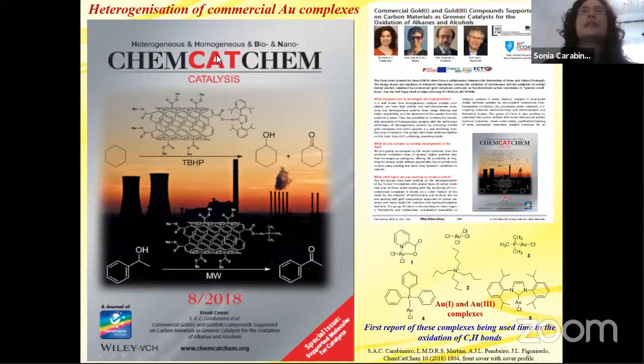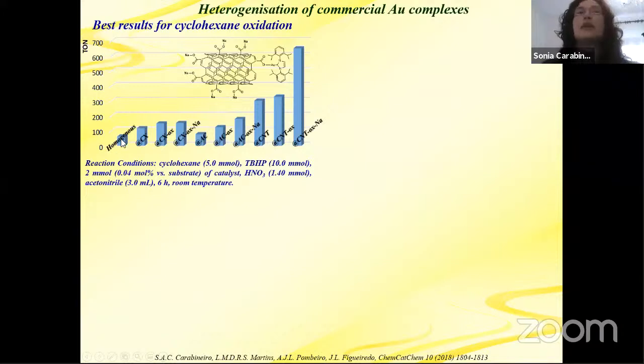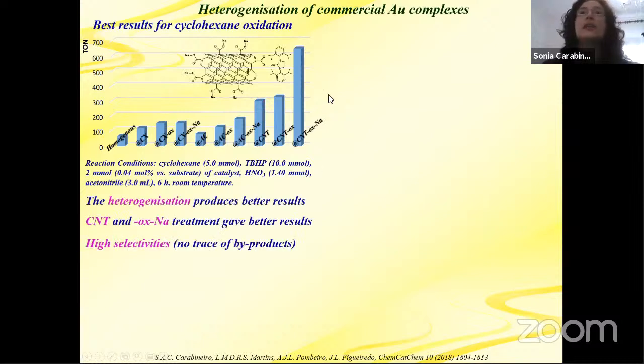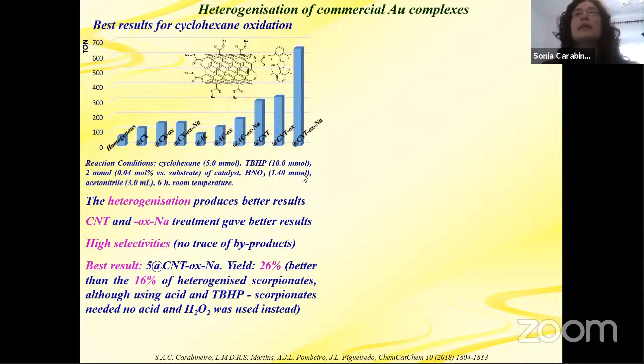So here, some example of results with the heterogenization of this complex on the carbon nanotubes. We see here again homogeneous, and if we heterogenize, we obtain better results. So heterogenization is better. Again, carbon nanotubes give the best results, especially with this oxidation treatment with sodium hydroxide, and again high selectivities with no trace of byproducts. And the best result was this complex with a 26% yield, which was better than the 16% of heterogenized scorpionates